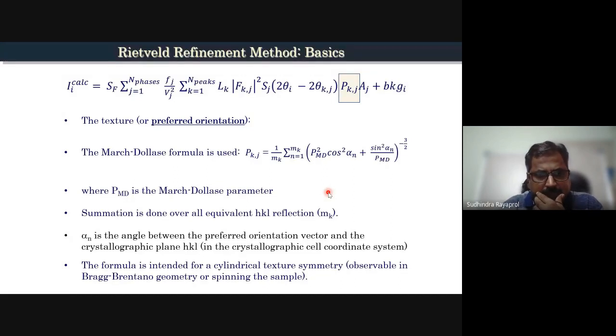If it is small in measure, it can be refined and you can actually quantify how much preferred orientation you have. But there is a limit to that. You cannot have a very strong peak and the rest of the peaks very minor. It will give you false information.